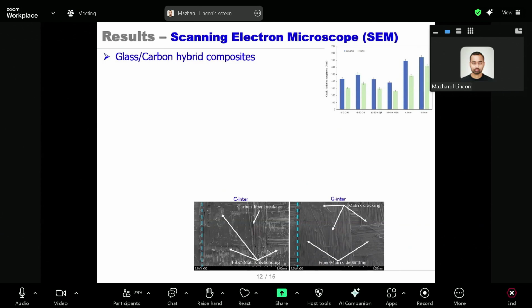The reason behind it is the fracture initiation toughness equation. If we see the fracture initiation toughness equation, it's directly proportional to the crack mouth opening displacement. Now, glass fiber is more ductile than carbon fiber and can deform more. That's why G-inter composite shows higher crack mouth opening displacement, and since it is proportional to fracture initiation toughness, higher fracture initiation toughness is observed for the G-inter composite case compared to C-inter.